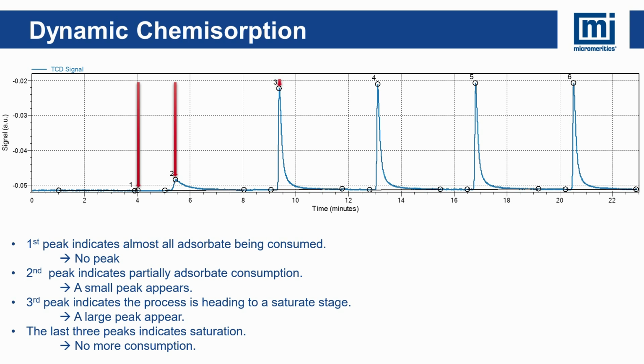Now on the saturation stage, which is the last 3 peaks, the final injections show a saturation plateau, where the reaction is essentially complete and the catalyst has reached its maximum adsorption capacity. The eluted peaks do not significantly change in height, meaning that no additional hydrogen is being adsorbed, and the system has reached a state where the platinum-alumina surface is fully saturated with hydrogen.